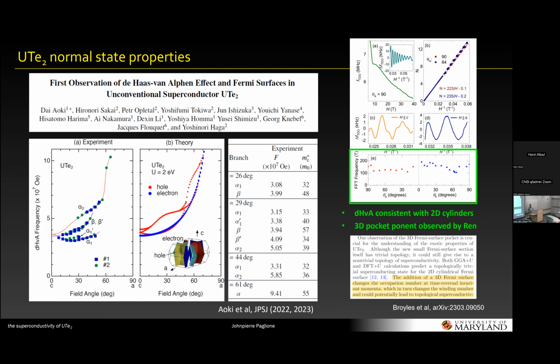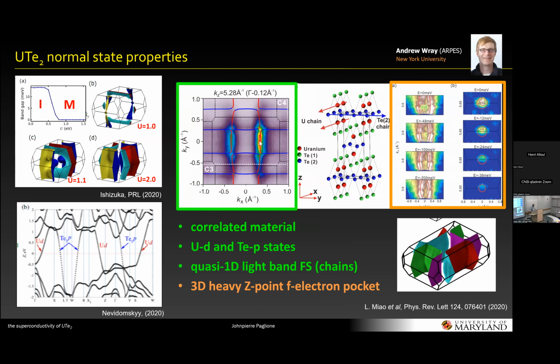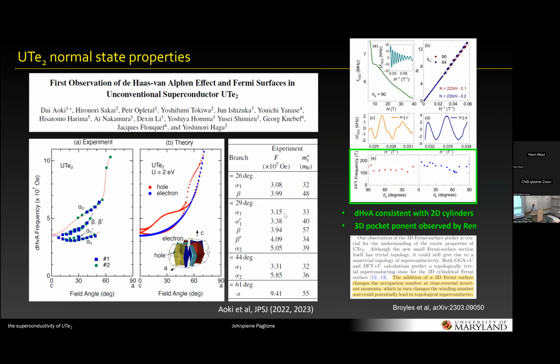So at least my understanding, if I go back one, these dispersions seen in ARPES are quite light, but ARPES probably doesn't have the resolution to see the hybridization right near the chemical potential. It's giving you the hybridized heavy states that are actually observed in quantum oscillations. And in passing, Sheng's group at Washington has also claimed to observe these small pockets that have F weight. So this is a current debate.